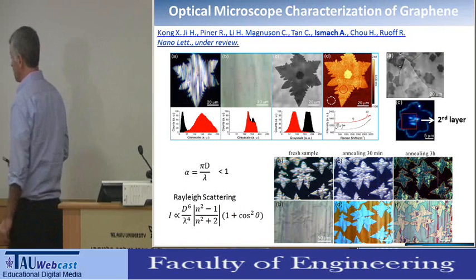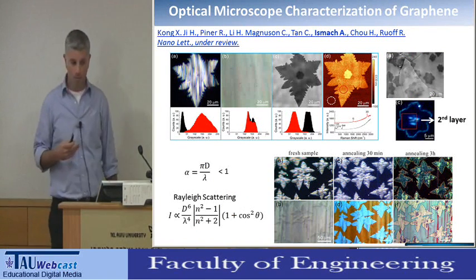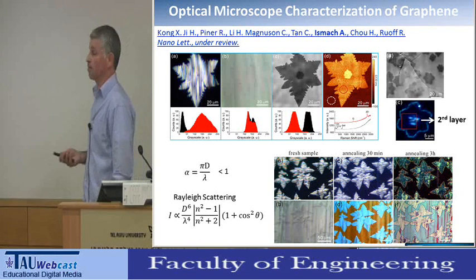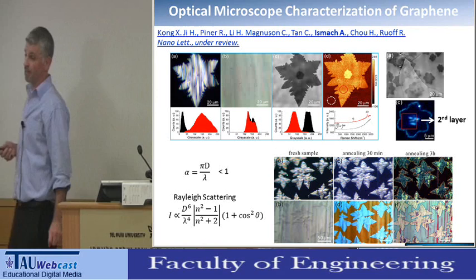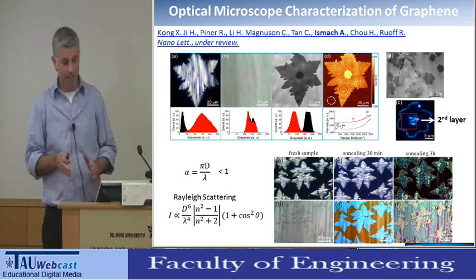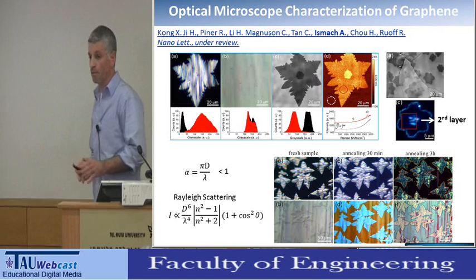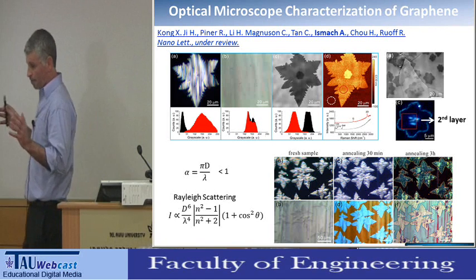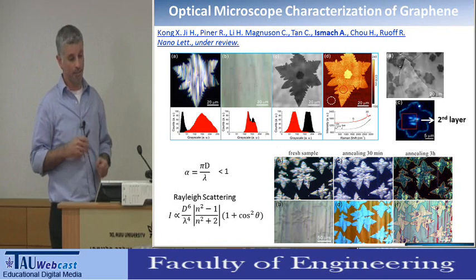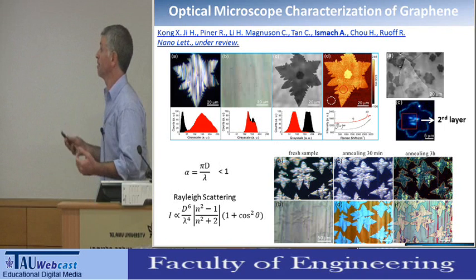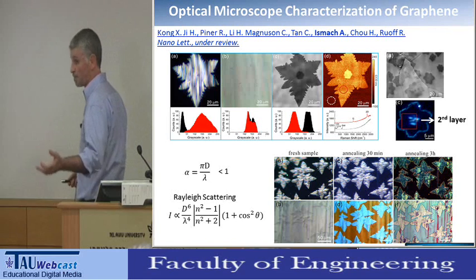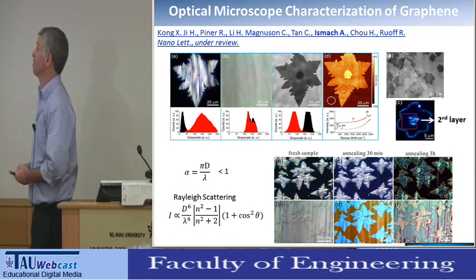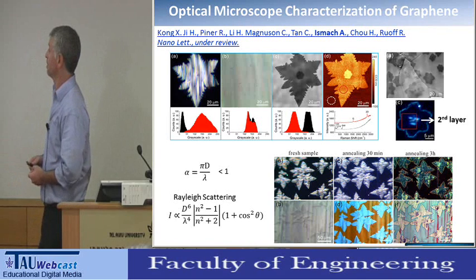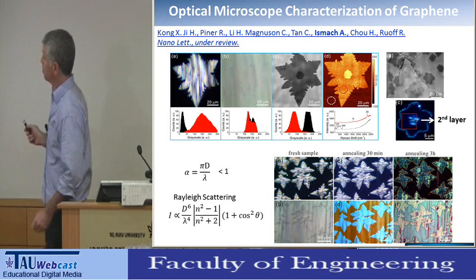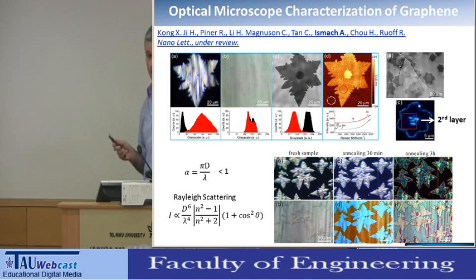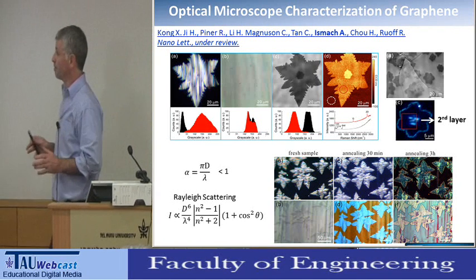Now, we are always looking for different ways to characterize our films. The characterization of these atomic films is not trivial, and I must say that the case of graphene is pretty good, because we have a very good set of tools to characterize the different aspects of graphene and few graphene layers, like Raman spectroscopy, that works very good for graphene and not for other materials, as I will show you in a minute. But we can show also that by dark field optical microscope, we can in fact achieve a lot of information.